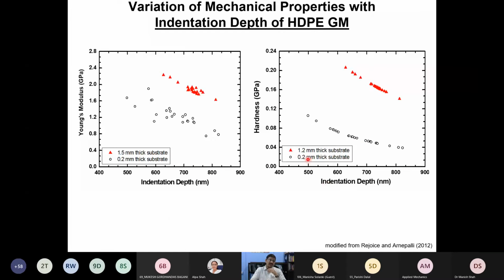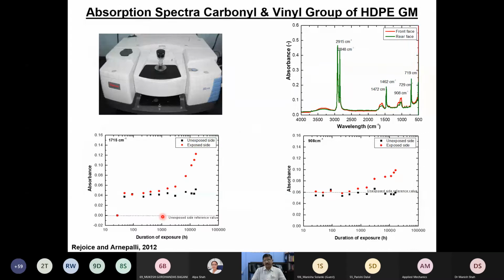So we plotted the role of depth of indentation on the hardness as well as modulus. And we saw that when there is something, then ultimately we optimize this particular depth of indentation to investigate further. Now we have noticed that there is a change in the modulus. How do you substantiate the measured change in the hardness or modulus value? For that matter, what we did is, if at all there is a change in the modulus at the surface level, obviously some molecular level changes might have happened to the polymer on the surface.